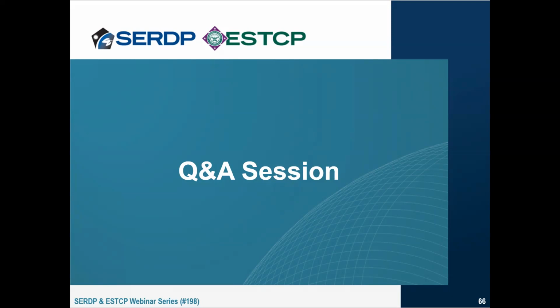We have a few related questions. Will Class G in the revised 23377 include an outdoor exposure requirement? If so, how long? Or have you already established a correlation between your test and outdoor or in-service performance? Yeah, thank you. We have already established that correlation. And so my intention is that there is no outdoor 1 or 2 year test. In fact, the only test that we're adding is shorter than the current scribed flat panel corrosion test. And that's 500 or maybe 750 hours of galvanic panels in the B117 and the GMW cyclic salt fog chambers.